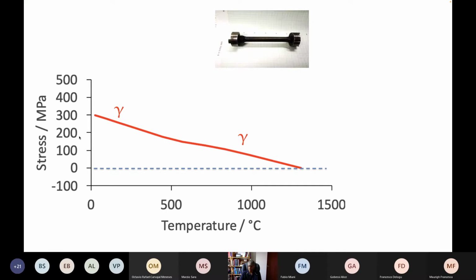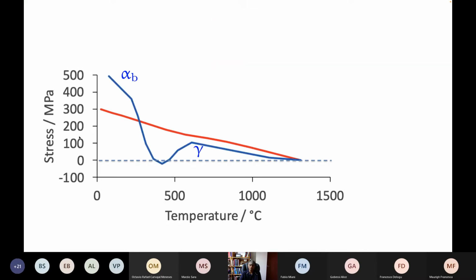Now, supposing you do the same experiment with a steel which transforms during the cooling process. Okay, so this is now a bainitic steel, and once again we get the rise in stress due to thermal contraction. But as soon as we get the onset of phase transformation, that compensates for the thermal contraction, and we get a reduction in stress. However, when the phase transformation is exhausted, that means all the austenite has gone, the stress begins to rise rapidly, okay? And we end up with a large residual stress at room temperature.